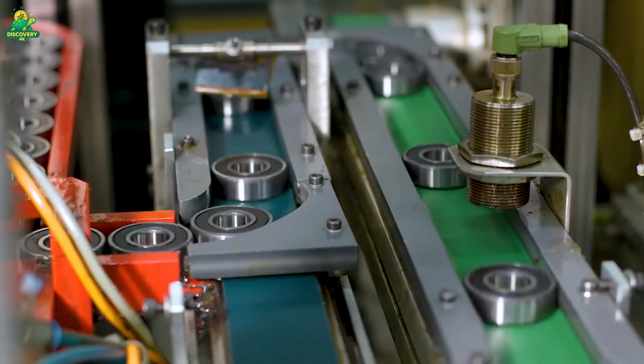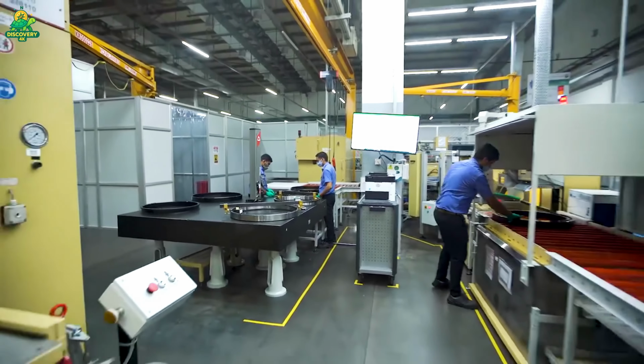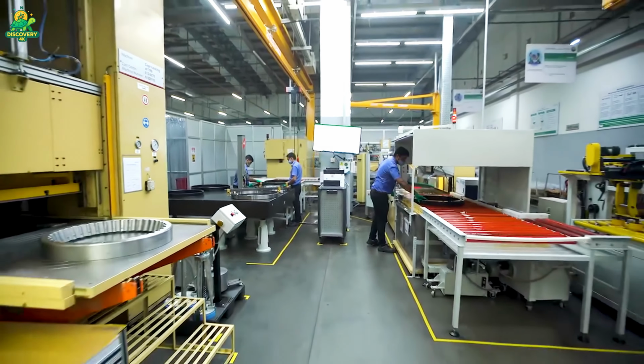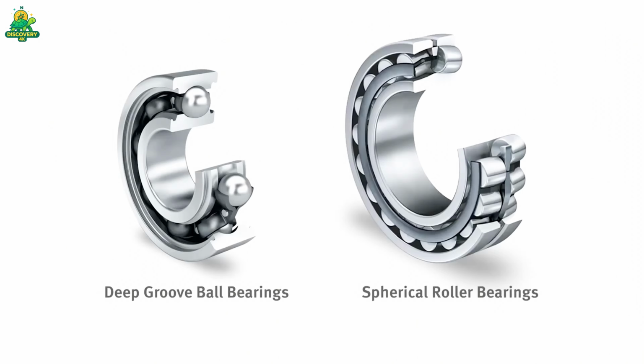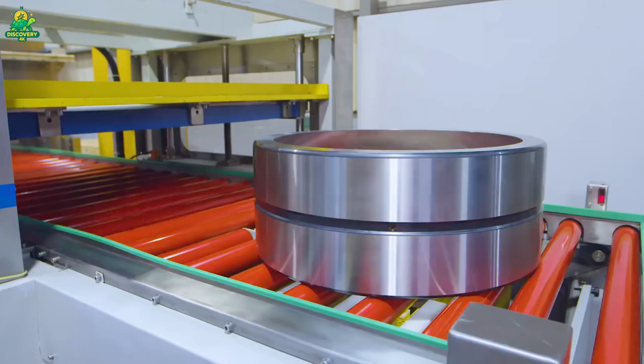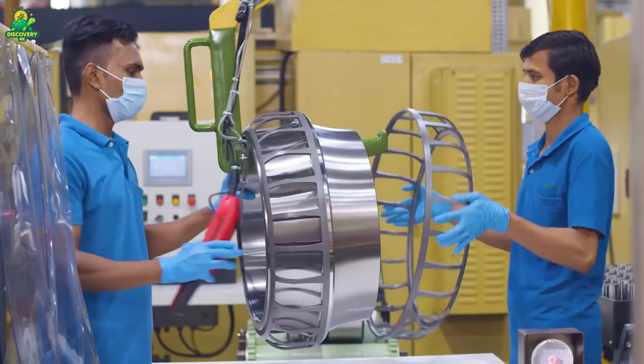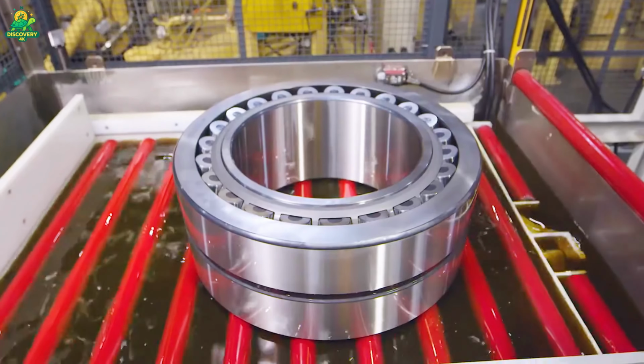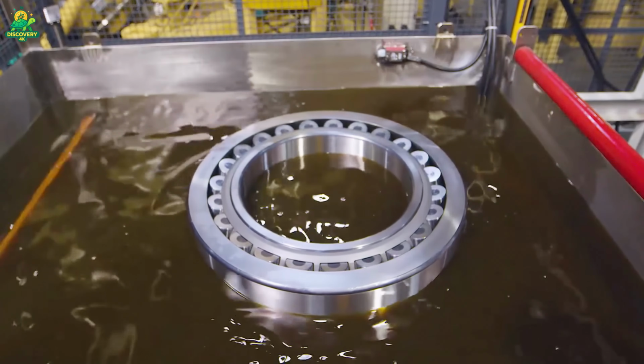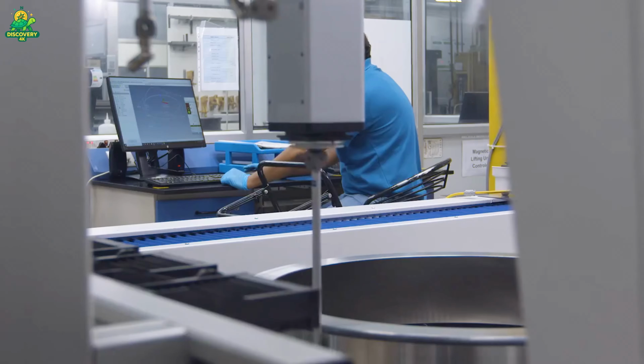Once hardened, it's time for precision grinding, the most critical stage in bearing production. Grinding machines fitted with diamond wheels remove microscopic layers of steel, refining each ring's surface until it's mirror smooth. The tolerances here are astonishing, within 0.0001 inches, 2.5 microns.